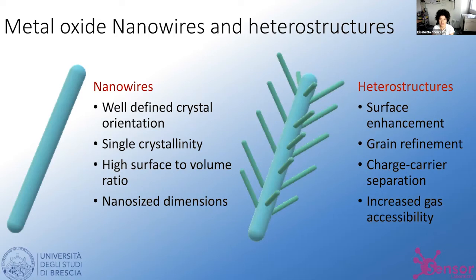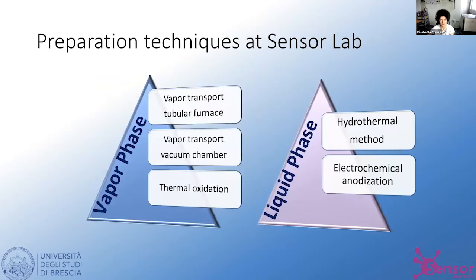Nanowires and heterostructures are interesting because in the case of nanowires, we have well-defined crystal orientation, and we can have them single crystalline, so stable over long-term operation. And we can have also a high surface to volume ratio. And it's easy to have nano-size dimensions of these nanowires. In heterostructures, like in this image, for example, we have surface enhancement, grain refinement, and charge carrier separation, and increased accessibility of gases into the nanostructures.